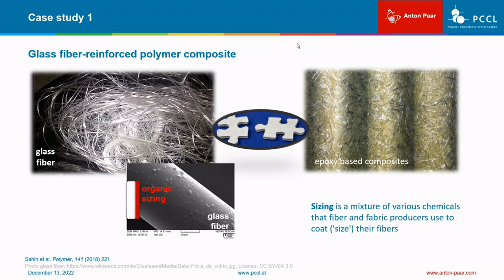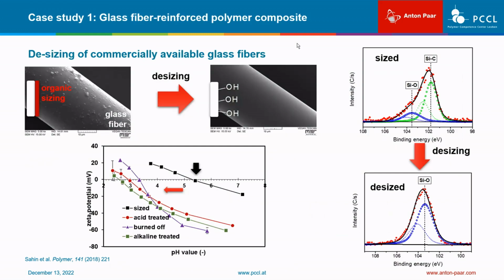In this study, the Zeta potential was used in the characterization of two steps of fiber surface modification. The glass fibers were provided by the manufacturer with a protective organic coating, the so-called sizing. In order to be able to carry out modifications on the glass fiber, this sizing has to be removed. In this first step, the progress in the desizing of the glass fiber surface could be monitored by Zeta potential measurements. As a complementary technique, the change of the physical chemical properties of the glass fibers due to the desizing was also monitored by X-ray photoelectron spectroscopy.